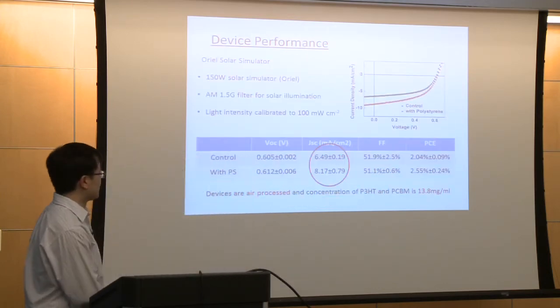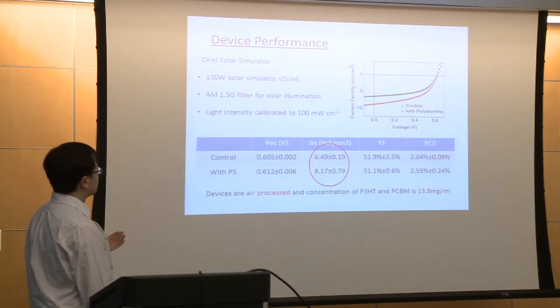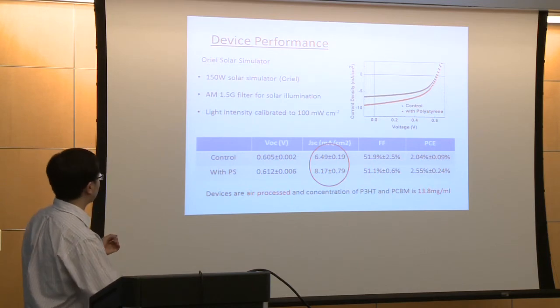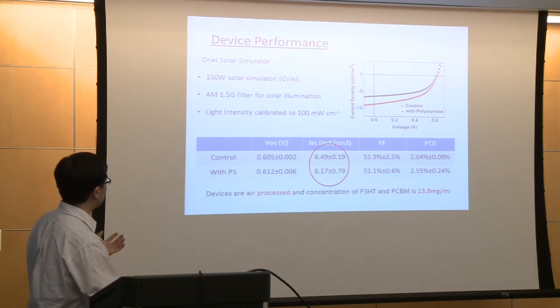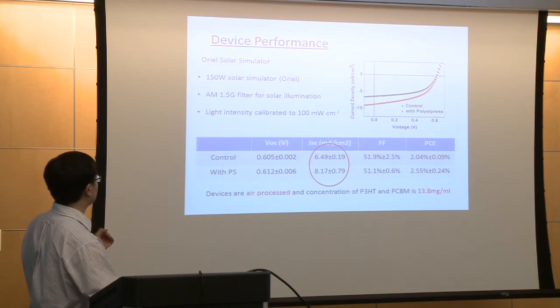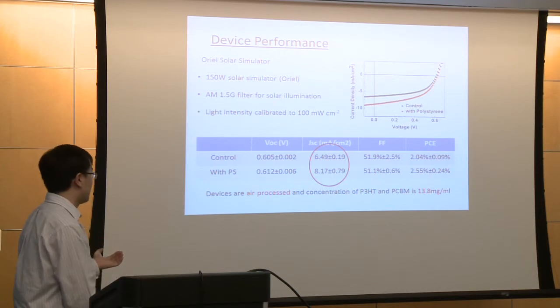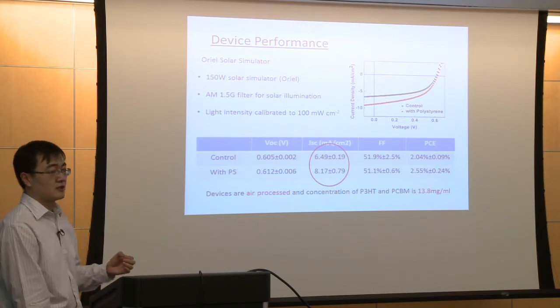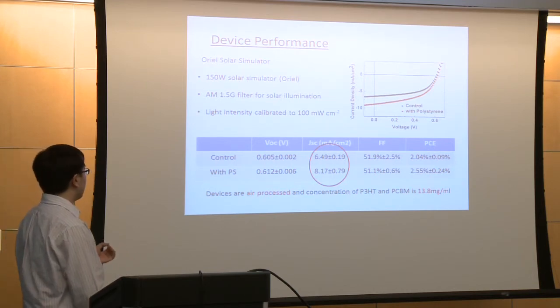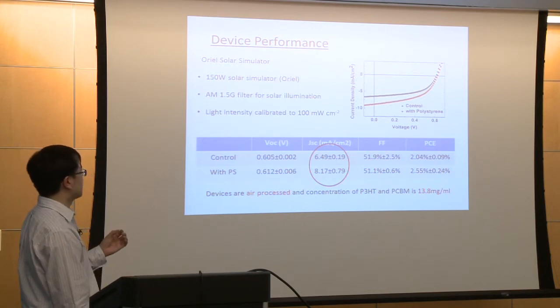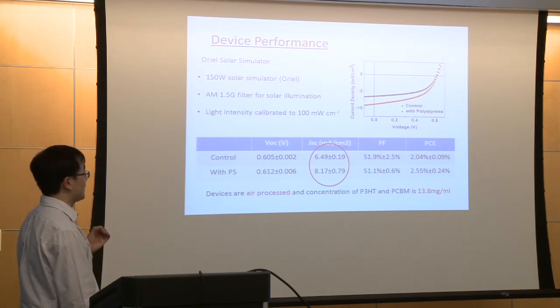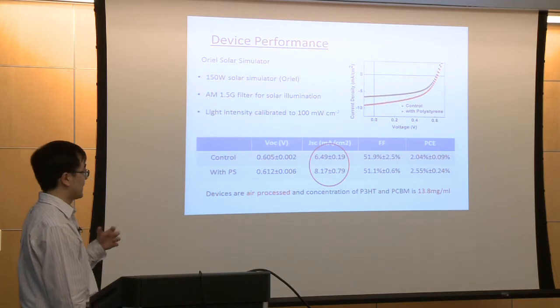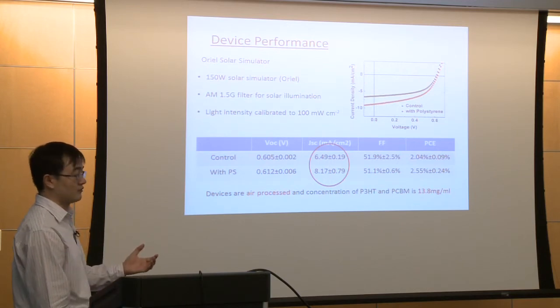Then we measure the performance. We use the solar simulator from Oriel company, and this station consists of a 150 watt solar simulator and one AM 1.5G filter for the solar illumination. And we adjust the light intensity to 100 milliwatts per square centimeter. That's similar to the intensity from the sunlight.